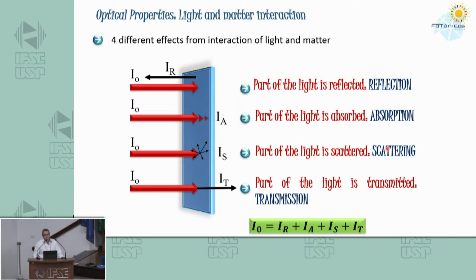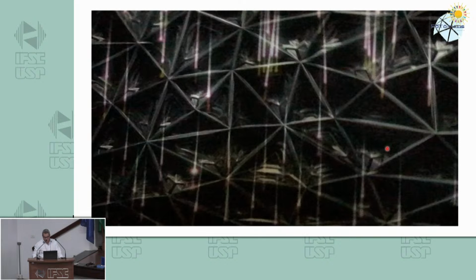I will talk a little bit about scattering, because some of the glasses we are interested in are nano glass ceramics. So we need to control the size of these crystals to have good optical properties. And related to the question that Serbena asked Andrea, usually if we have nanoparticles inside the glass, to avoid a lot of scattering, we need to keep the size of the nanoparticles below 100 nanometers, okay? So, in fact, if we need to take advantage of the nano size of the crystals, we are going to work around 20 nanometers up to 50 nanometers, and so we can take advantage also of the nano size of the crystals, okay? So let me see if it works.